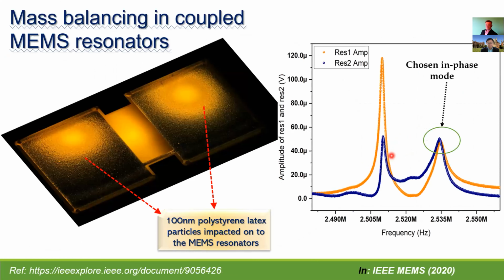But the input referred stability, which is the minimum mass which can be estimated based on the frequency shift output metric and the amplitude ratio shift output metric, is verified for this experiment. Now, the other important thing to notice in these resonators: when particles get deposited on the resonator surface, the resonator surface fills quickly. So if the concentration of the particles is very high, the sensor lifetime will be reduced. That is, we will have to replace these resonators immediately.